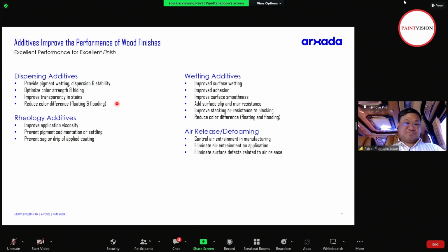Wetting additive improves substrate wetting for difficult substrates to coat, such as substrates that have oil contamination or silicone contamination. Especially for wood, we have tannin, which has a lot of oil on the surface that can interfere with adhesion. So it improves adhesion by the substrate wetting concept. It improves flow and leveling so you get smoothness, gloss, and color development for your glossy system. Also, some of the products that we provide give surface slip so that you can get block resistance, stain resistance, or stacking resistance. And of course, it goes along with those dispersing concepts, as the wetting additive also helps you reduce color difference, so the anti-floating and anti-flooding that we're talking about.